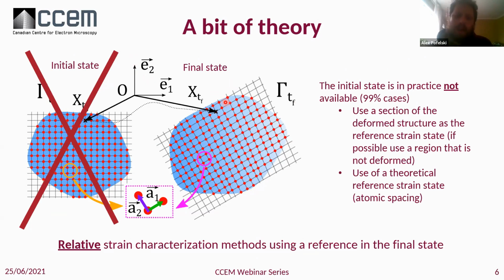So the solution that has been found is to use a reference state already in the final state of deformation. Two cases can be explored here. The first one is to use a reference inside the material at the final state. It is possible that in your final state, you have a part of the geometry that didn't undergo any deformation. Sometimes yes, sometimes not. Since we don't have access to an initial state, we need to select a certain reference. The other option is to use a theoretical reference for the strain state, for example, just taking the crystal structure at its relaxed state, and comparing it to this theoretical reference.